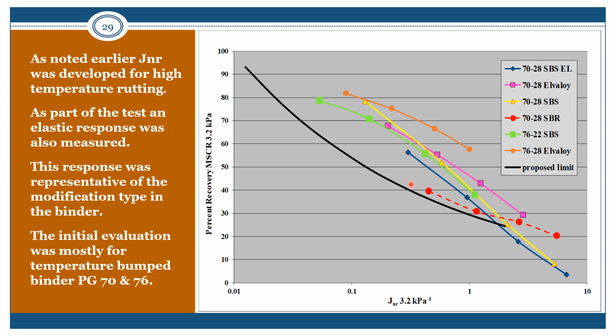Now, if you look at the PG 70 grade binders in the M320 grade, you start to see some very big differences between these properties. With the Jnr values, at 76 degrees, for example, this SBS Elvaloy combination wouldn't even be an S grade. It's not till you drop down to 70 degrees you start to get an S grade. Whereas this 70-28 Elvaloy, even at 76, is an S grade. So it really shows how the base asphalts and the formulations make a big difference, and the M332 specifications really start to show some of these differences. And again, these are based off of existing asphalts that were used on roadways back in the early 2000s.